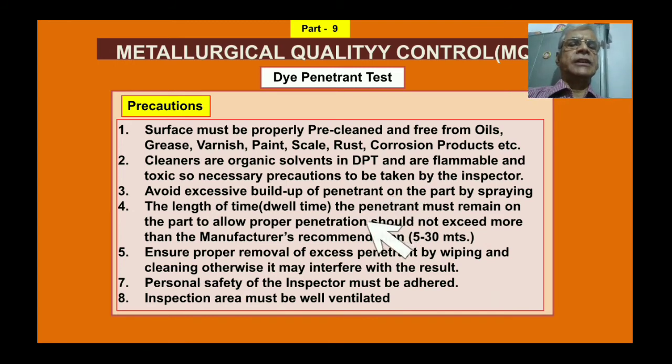The fourth point is the length of time. The penetrant must remain on the part to allow proper penetration, and should not exceed the manufacturer recommendation. What is dwell time? Dwell time is nothing but the time you keep penetrant on the surface so that it gets into the cracks. So that also should be as per manufacturer recommendation. But in general it is 5 to 30 minutes. You have to keep that penetrant open to the surface so that it goes inside the crack.